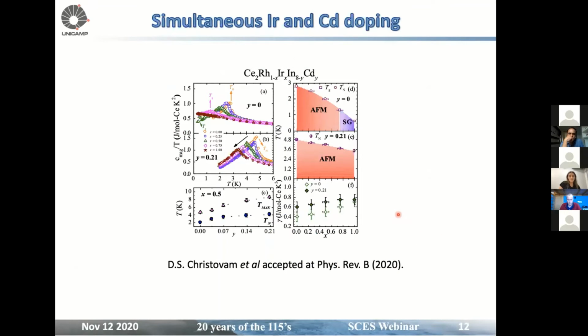So we did experiments with both iridium and cadmium doping. So that's a beautiful phase diagram in which Dennis compiled all the beautiful data. So we could see Tmax increasing, and the Sommerfeld coefficient increased a little bit as a function of iridium.